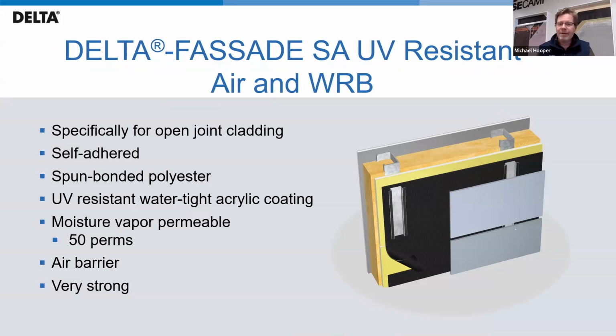In colder climates, typically you have continuous insulation. If it's a fibrous insulation, you have to use mechanically attached. You won't get a good bond with any fibrous insulation, such as mineral fiber. However, if you want to use EPS, XPS, anything like that, this sticks perfectly well to that. I should mention the perms is significantly lower because the adhesive that's applied to these membranes, despite the membrane being the same, does lower that permeance overall. And this still comes in at a quite high 50 perms.